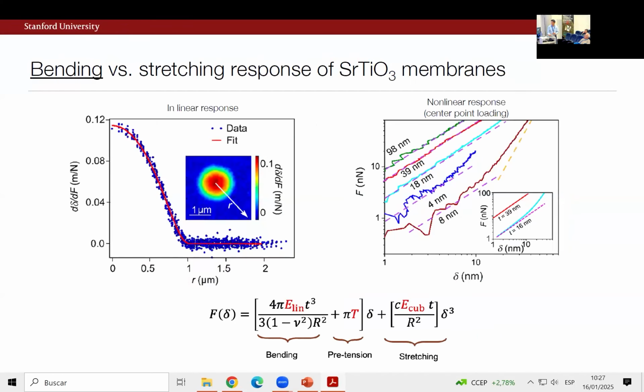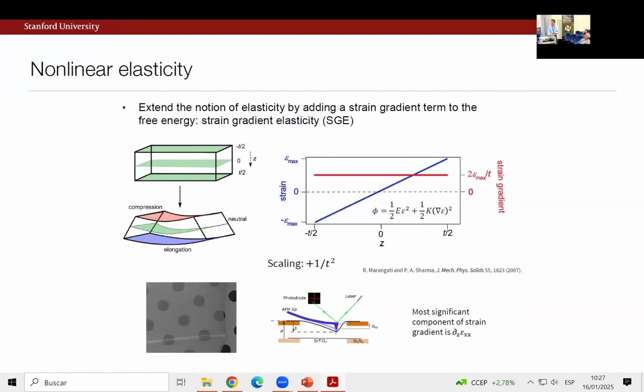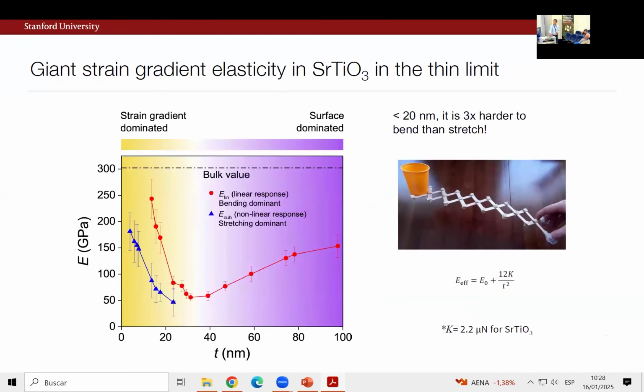There was one key thing I forgot to say back here that I'd like to come back to. This gradient term, this strain gradient term, right, this bending that I told you about, what's important and lovely about these membrane geometries is their contribution to the free energy is scaling as 1 over the thickness squared, right? And so it's kind of consistent with your intuition that it's easy to bend this floppy, thin material around, but this is actually quite relevant for why I think we have many opportunities to go after new things here.